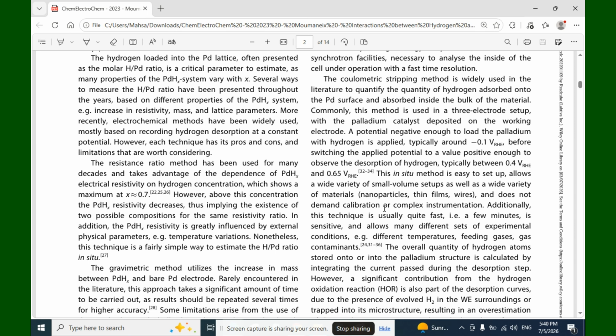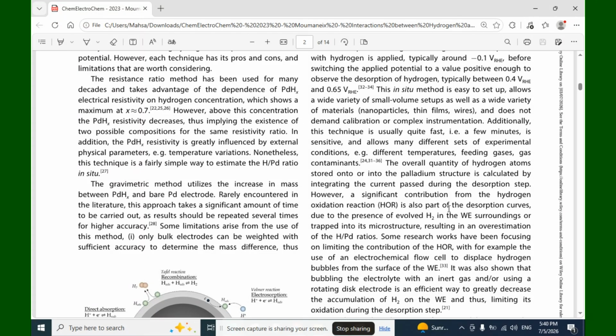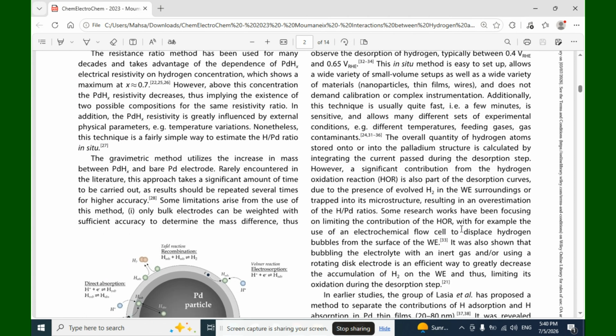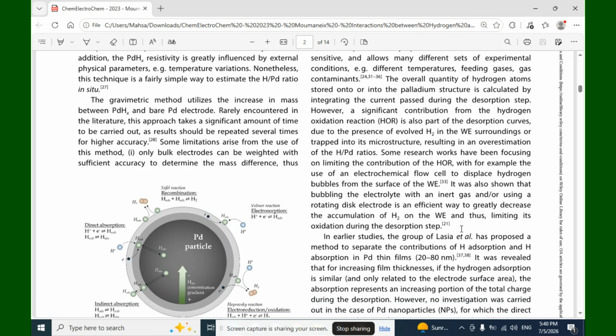However, a significant contribution from the hydrogen oxidation reaction is also part of the desorption curves due to the presence of evolved hydrogen in the surroundings or trapped in the microstructures, resulting in an overestimation of the hydrogen palladium ratio.